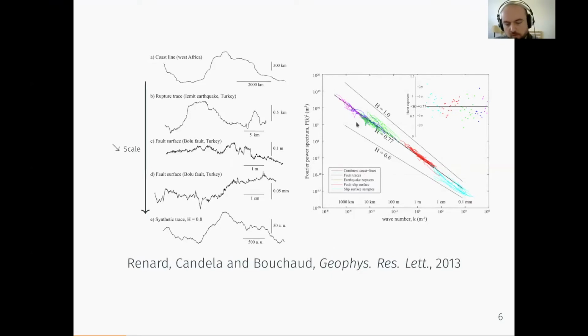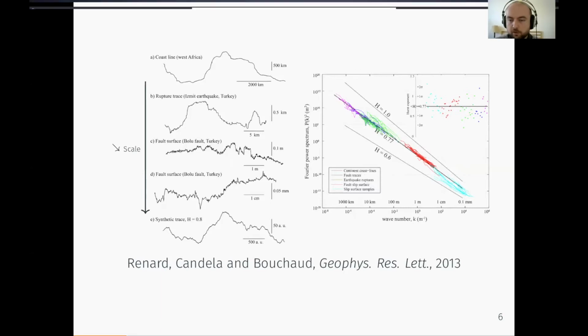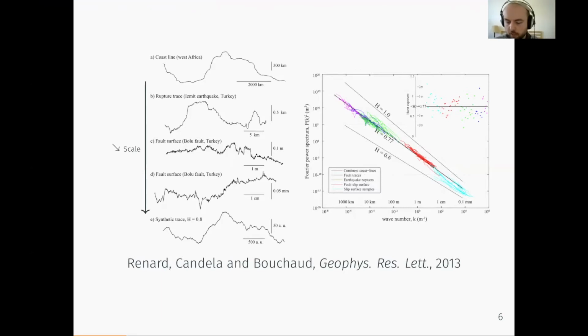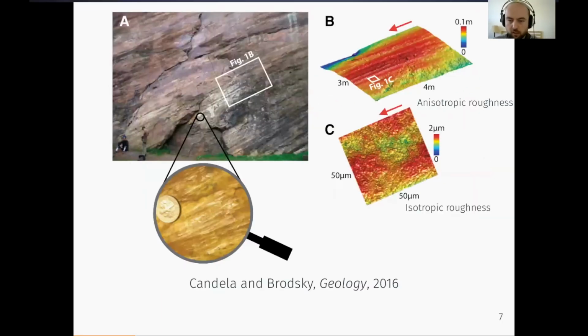Since roughness is so important to friction and wear, you might think that since it's scale-free as well, friction and wear might also be scale-free phenomena. However, this isn't the case. To illustrate this point for wear, I chose this work of Candela and Brodsky, where they did measurements of roughness of a geological fault. Here you see on this picture and on this topography map, there is anisotropy because the fault, before being exposed, used to be sliding.